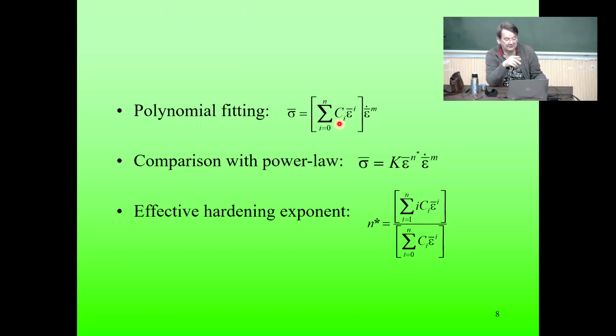At least this kind of strain hardening curves with polynomial fitting work very nicely. If you compare this with the usual power law Hollomon type of function, you see there's a big difference. Here there's just one single n exponent, while here there are 1, 2, 3, 4, these integer number exponents, many of them, and there are several Ci parameters, of course. But one can compare that if one considers using this formula with n variable, and n is n star. If n star is varying using this formula, then actually you can use this formula for the perturbation, but you have to consider that n is variable.